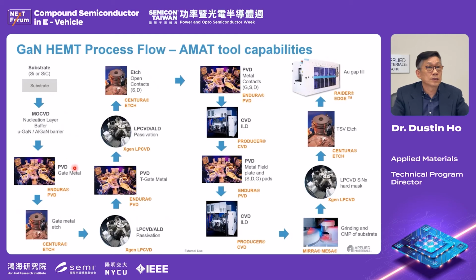And here is some Applied Materials capability to do this. We do have the PVD for the aluminum nitride buffer layer. For gate metallization, a lot of people are concerned about charge damage, so maybe use the e-beam evaporator. But actually, we have long stroke PVD, and it can reduce the charge damage.